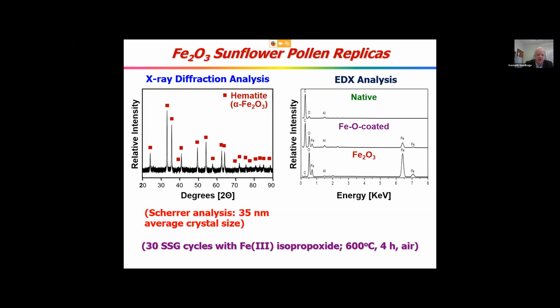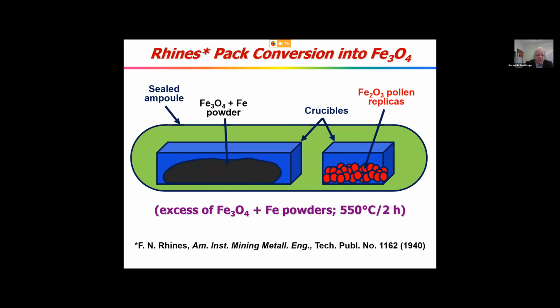We wanted to make a stronger magnetic material, magnetite. So we borrowed a trick inherited from Fred Rhines, a metallurgy trick called Rhines pack. We take Fe2O3 pollen particles, put them in an iron ampule along with an excess of magnetite and iron, heat it up to 550 C.